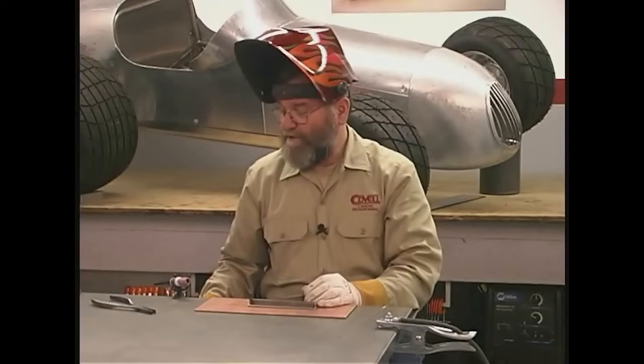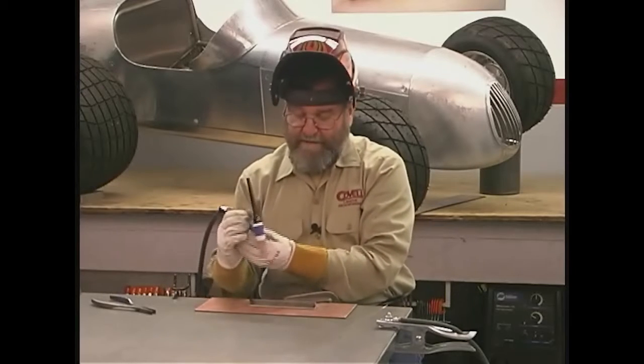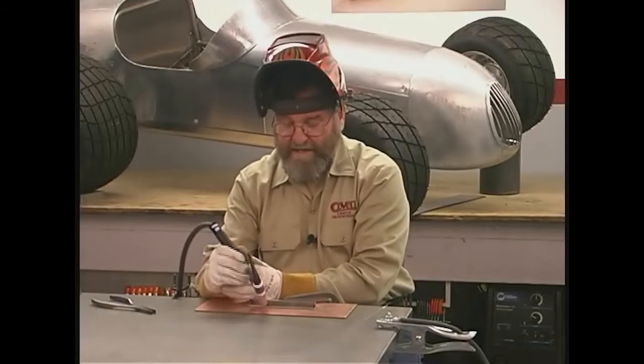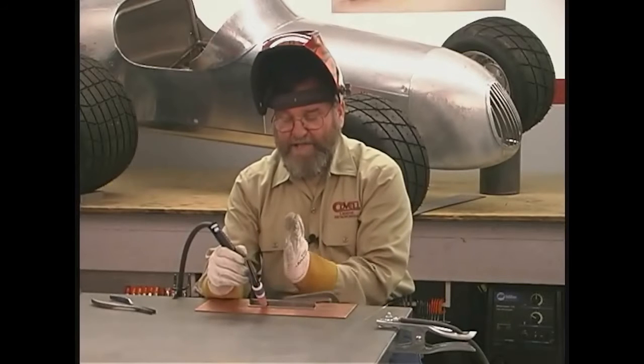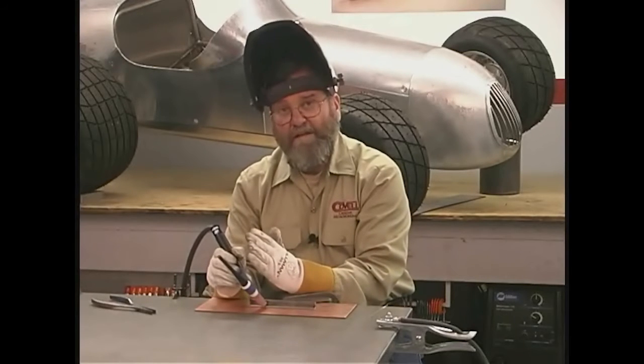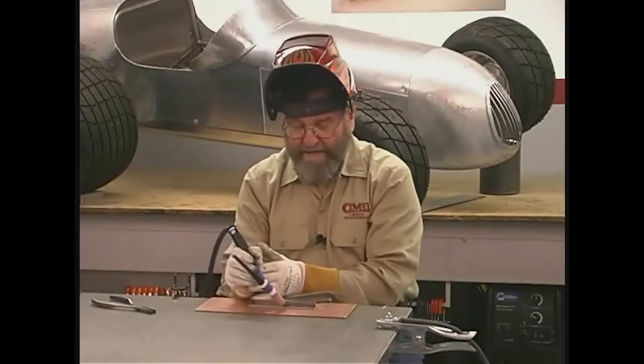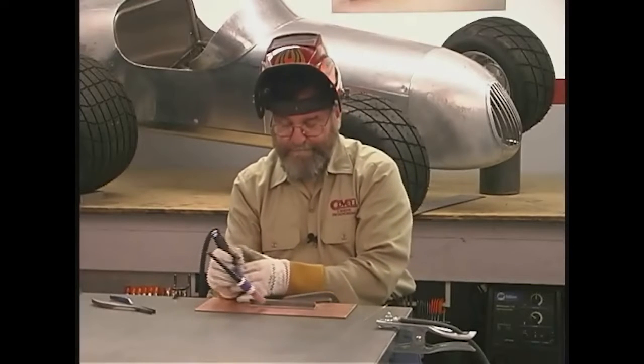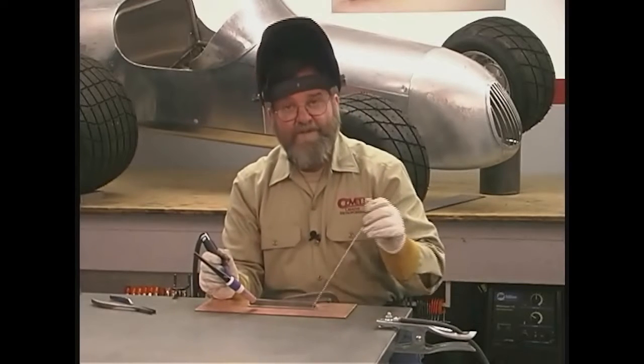Okay, let's talk about the torch angle next. The torch should be angled halfway between the horizontal portion of the T and the vertical portion. So I want about a 45-degree angle in this direction. And then also I want that 15-degree angle off of vertical pointed in the direction of travel. The filler rod I'm using is 1/16 diameter, 308 stainless rod.